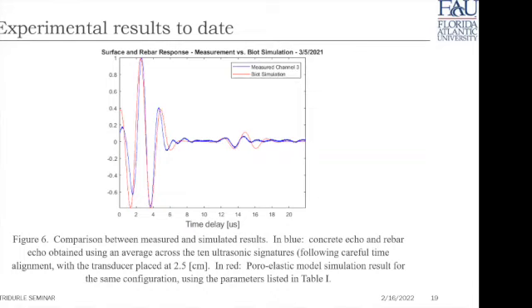Yes. Which is, with this approach, would you be able to detect early age cracking, which may be only like 200 microns and propagating, in the early stage? We should be able to, and for the following reason: the cracking itself is producing a change in the acoustic and mechanical impedance of the medium at the interface between the concrete and the rebar. And that causes a fairly significant change in the signature of the response.